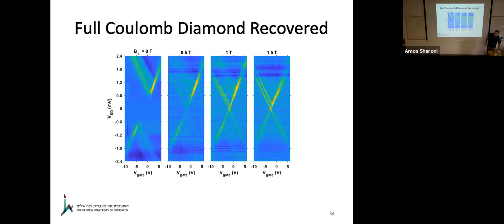Okay, what is doublet C? That doublet is the excited state of the dot. Now, if you apply a magnetic field, the dot Zeeman splits. What you see is the Zeeman splitting of the dot, and you can actually extract the g factor of the dot and everything. So it's actually pretty straightforward to calculate. You just look at the energies of this Zeeman split state.